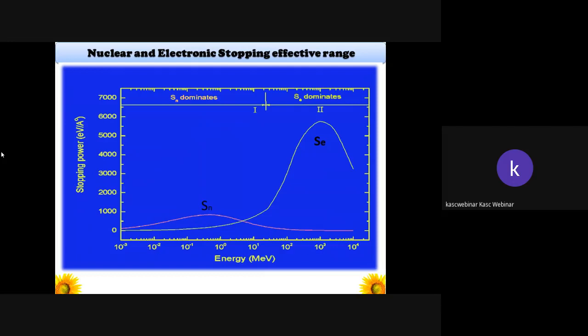Then this picture clearly indicates the difference between the impact of a swift heavy ion when compared with the nuclear energy loss at kilo electron volts. Up to 1 mega electron volt, this nuclear energy loss is dominant inside the sample, and after that the electronic energy losses are dominant when compared with the nuclear energy loss.